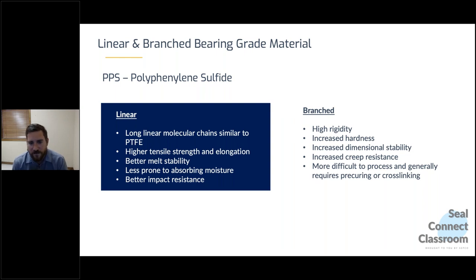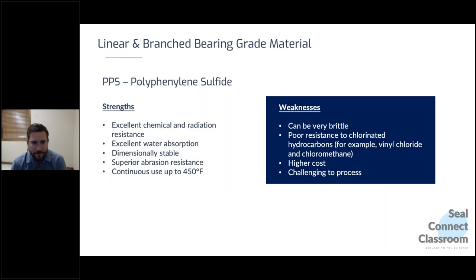The other side of that is there are branched forms of PPS, which have high rigidity. They're very hard materials, harder than the linear versions, with really, really good dimensional stability and improved creep resistance, but they are more difficult to process. These branched versions generally require pre-curing, they require cross-linking, and they are almost always much more brittle. So at impact, they will break.